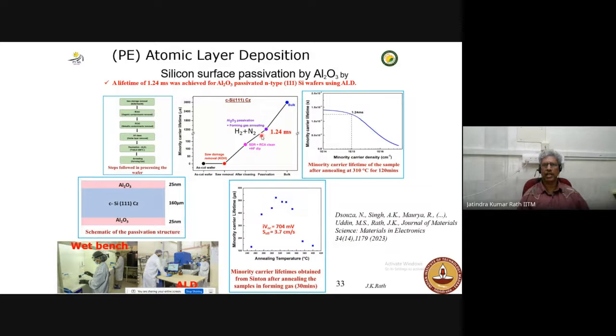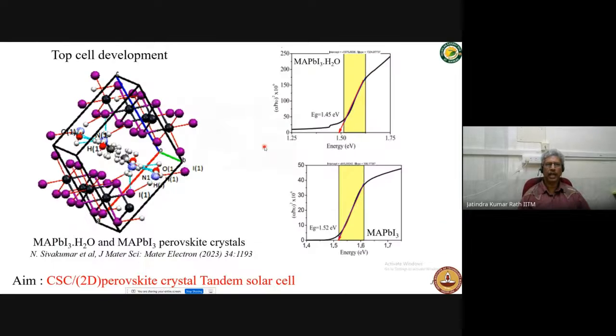So you can see the lifetime of the wafers after the passivation layer is 1.24 millisecond, which is pretty high, and this is almost giving an implied VOC of 704 millivolt. This is one of the highest. It's highest in India anyway. It's also one of the highest in the world. This gives a good indication that we can make pretty high carrier selective contacts, but that's in progress now.